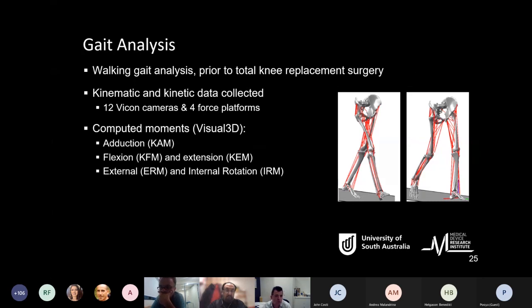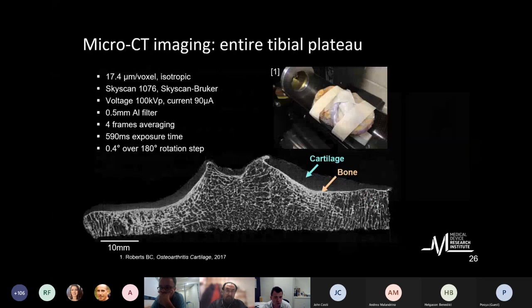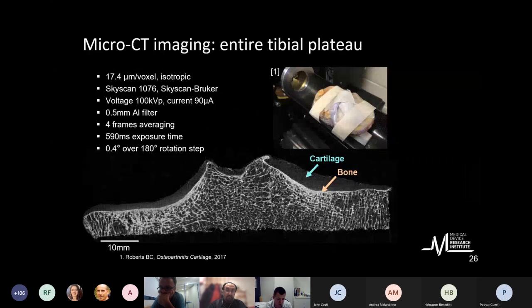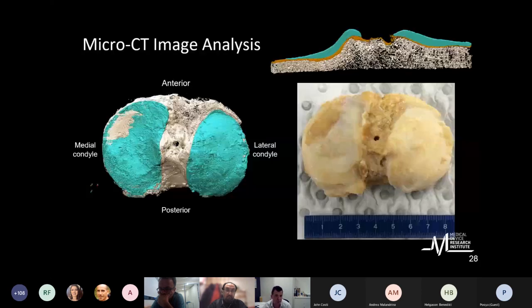So gait analysis was done prior to surgery, and the reason why we thought we can see cartilage is because when we developed a scanning protocol for Bryant, we saw that there was actually the cartilage above. By trying to maximize the signal-to-noise ratio for seeing the pores in the cortex, we actually are visualizing most of the cartilage. That gave us an indication that we can actually see it. And by thresholding it properly, you can actually look at the cartilage here in blue.